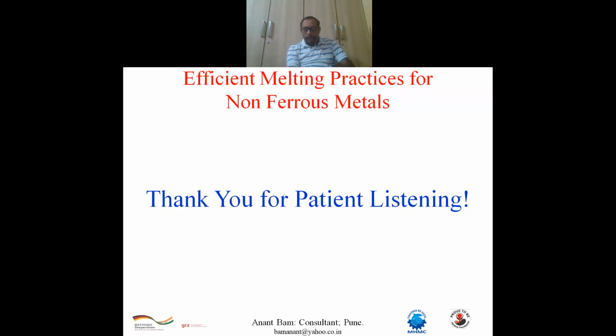Yeah, I have a question. Yes, sir. Sir, we are also doing the same practice. We are keeping the metal above the coil also. Now if we start keeping it below, the crucible capacity is around 150 kg. But our pouring time is too high. We are doing gravity die casting, where the average casting weight is about 500, 600 grams.